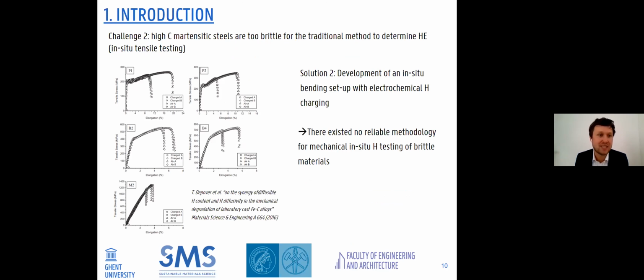So B2 stands for 0.2% of carbon, B4 is 0.4% of carbon. This was possible, but when we then go from bainite, so the B, to M, to martensite, it was possible to do in situ tensile testing when the content of carbon was 0.2. So for M2, we can see embrittlement when you compare the air tests with the charge tests. But as you can see, there is no graph of M4.